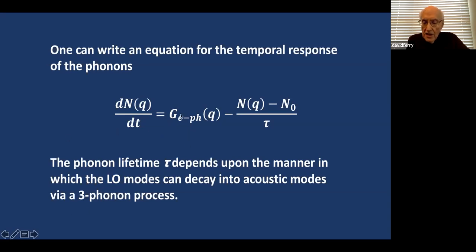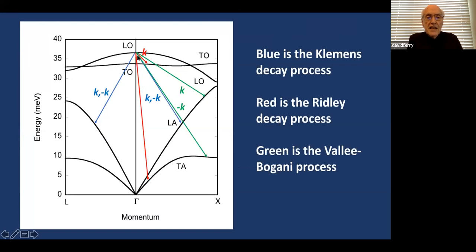So what is this 3 phonon process? Okay, well, there's several of them. Okay, this is that same spectrum for phonons I had before. Now, the oldest process known to us is the Klemens process, which is this blue curve. So 2 near 0 momentum LO phonons decay into 2 LA phonons with equal and opposite momentum. So the LA phonon has to have half the energy of the LO, okay? So the 2 of these add up to that energy, and the equal and opposite momentum give you nearly 0 momentum. That's called the Klemens process. It's the oldest. Then Brian Ridley came along and said, well, wait a minute, I could decay into a TO mode and a TA mode with the opposite momentum and still conserve energy. So that's the red curves, and that's the Ridley process, okay?